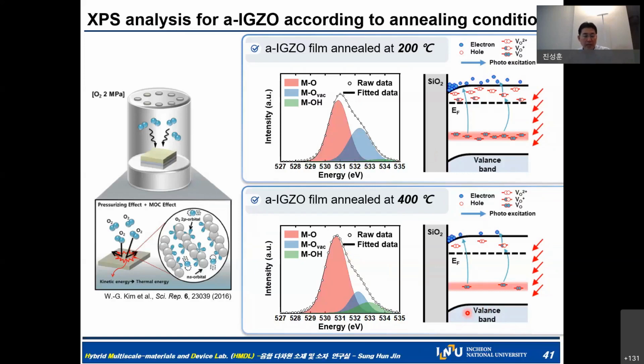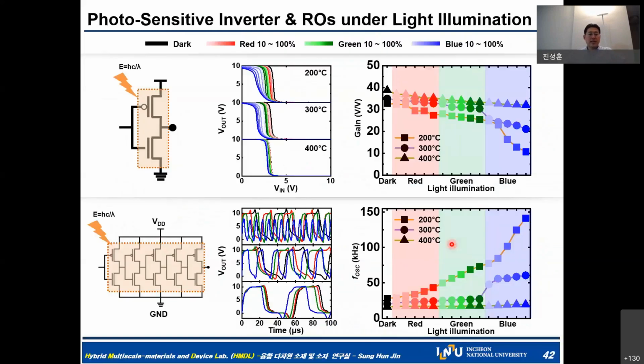So in between, under certain necessary conditions, we adopted 300 degrees Celsius. With this kind of condition, as you can see here, at 400 degrees Celsius the light frequency conversion property is negligible. However, at 200 degrees Celsius the photosensitivity is very amazing, but in terms of reliability it is very poor. So we have to choose the trade-off at 300 degrees Celsius.